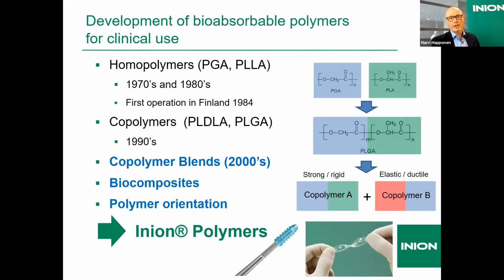The first polymers used in the implants were homopolymers, meaning that there was only one molecule in the polymer, either polyglycolic acid or poly-L-lactic acid. However, they were not completely optimal for bone fixation or surgical applications because of their degradation profile. PGA is very fast degrading and PLLA is very slow degrading. So the researchers developed copolymers from those polymers to obtain a more suitable degradation profile for the implants. And in the 90s, the copolymers of polylactic acid and glycolic acid were launched, and then the degradation profile was more suitable for medical devices.